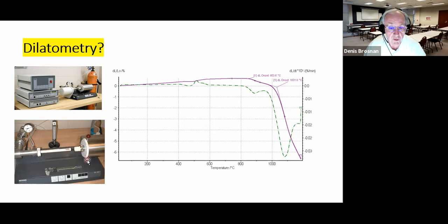The furnace is slid around this tube and it's heated, and you're continuously monitoring the length. So the graph here is showing the length of the ceramic. Notice the negative numbers, meaning we're expecting it to shrink versus temperature. So the purple line or upper line in this graph shows the ceramic expanding as we begin to heat it. In other words, it's upward direction, but it gets to a point of inflection here. The point of inflection is where shrinkage begins.